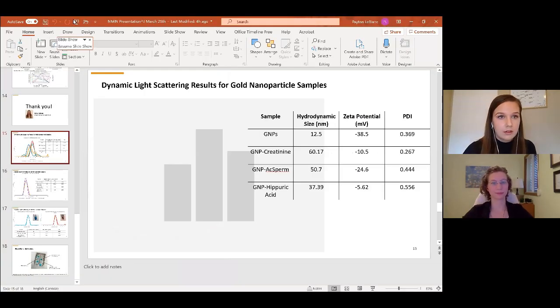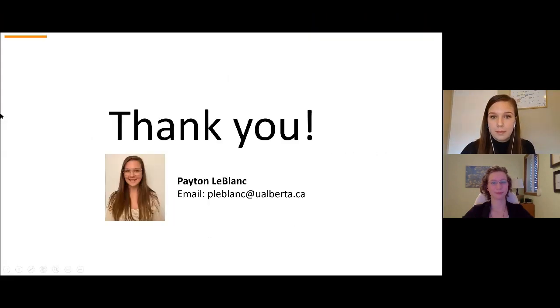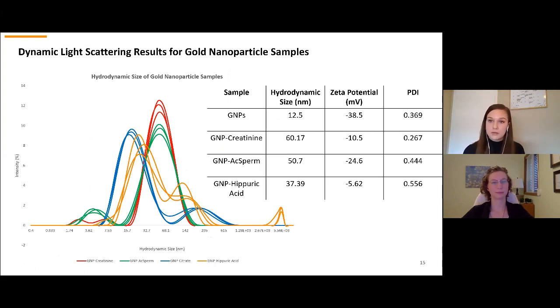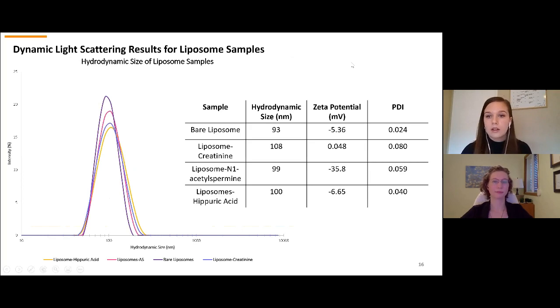So what we're considering right now is that gold nanoparticles, while they are very conductive, they also are a little bit more difficult to work with because they aggregate quite easily. And as you can see here, the PDI, which is a measure of homogeneity of our sample, is quite high. So not as consistent when it comes to developing a medical test. However, liposomes have a quite lower PDI and are a little bit easier to prepare because there aren't as many considerations we need to make in terms of buffers and what will cause them to aggregate.